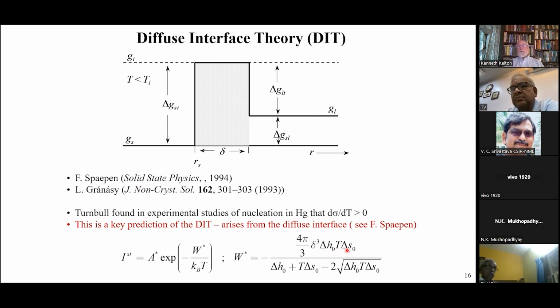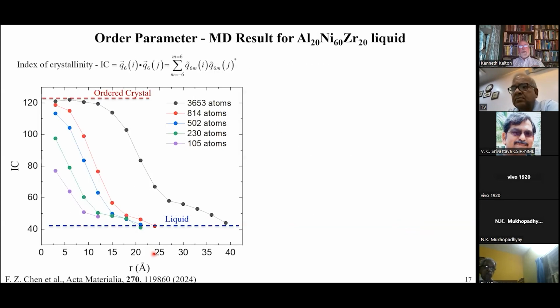It's a little complicated because these delta H zero and delta S zero are the width of the curves independently for H and for S. So as you go from the liquid to the cluster, that's the size of those clusters, and that's of that curve. But if you knew that, then you could calculate the nucleation rate much better than you can from the classical theory. So there is an alternative to the classical theory that's quite tractable.